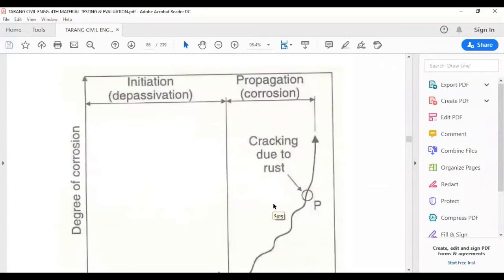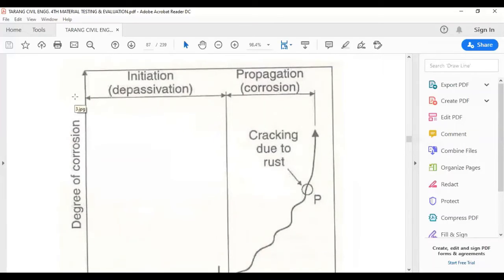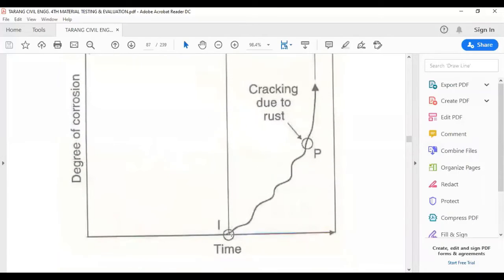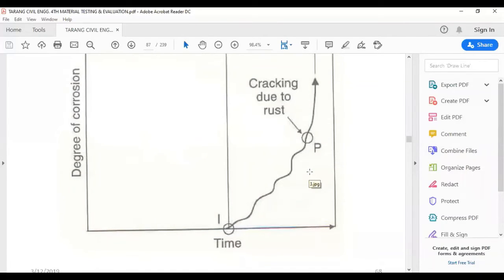So as you can see, it is the initial depassivation when the corrosion does not occur, but the chloride ions lose their energy in depassivating the stable oxide layer. But once the concrete has been depassivated, from this time till this time, propagation of corrosion occurs, and by this time corrosion starts occurring. As you can see, degree of corrosion is increasing, and at this point cracking starts to take place in the concrete.